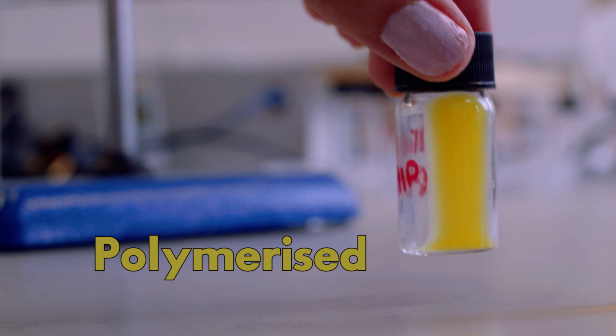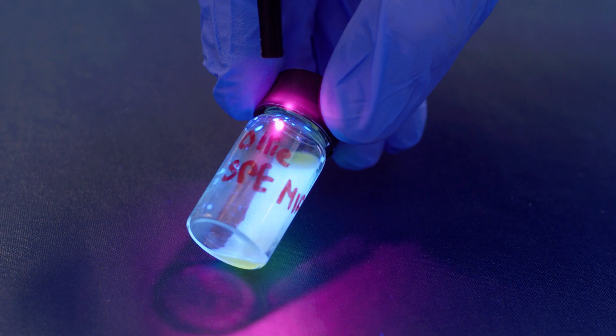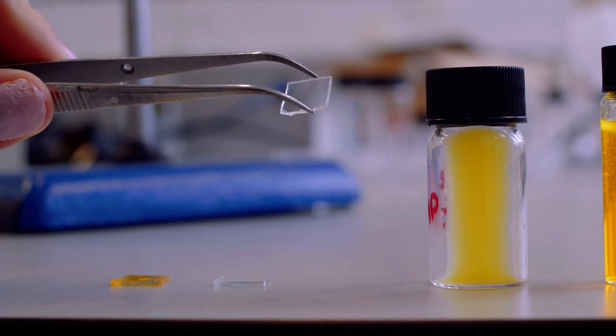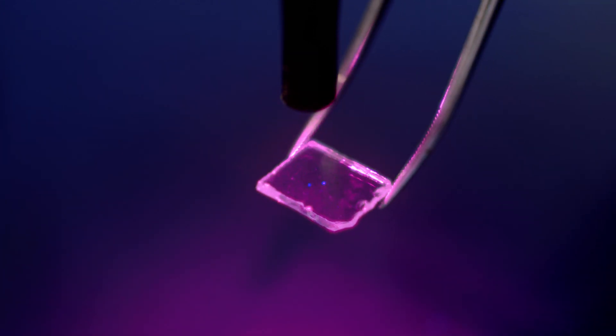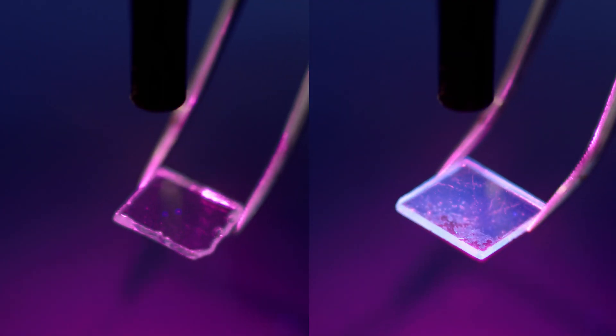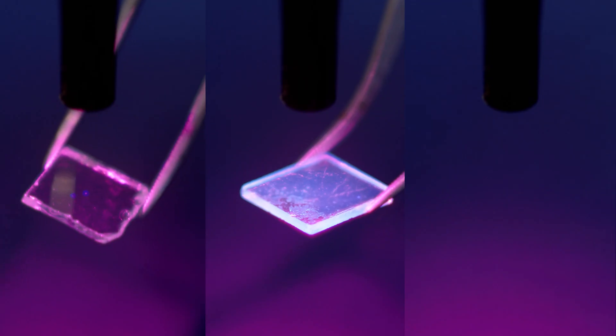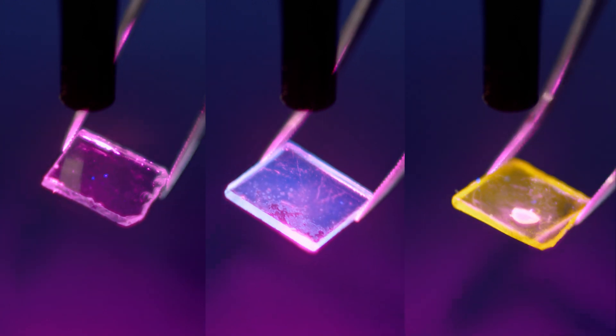This is a liquid, and as you can see it's very fluorescent because it's got a molecule in there called fluorescein. When we polymerize it and get a solid particle you can see that it's still very fluorescent but it's gone down a little bit. Then we take some of that solution and polymerize a very thin layer onto the electrode. The first one is a blank glass slide so it doesn't contain any polymer. The next one has a little bit of a blue polymer on it — you can see this blue shine — and the last one uses a yellow colour, also fluorescein. So you have a little layer of polymer that you can't see with the eye, but as soon as you shine UV light on it you see this lovely yellow colour.